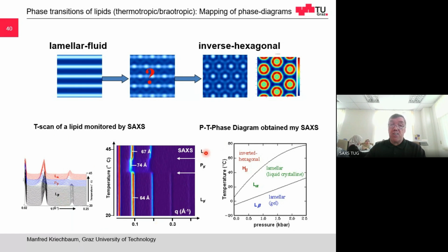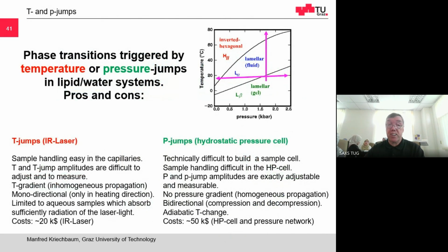And the conclusion of this is that we can map out the phase diagram, temperature versus composition or versus pressure. In that case, we have a temperature-pressure phase diagram with a lamellar phase. In that region, we have a liquid crystalline phase, and then we have a hexagonal phase. So slow scans, with heating, are used for mapping out phase diagrams. Well, I think I have to speed up a little bit.